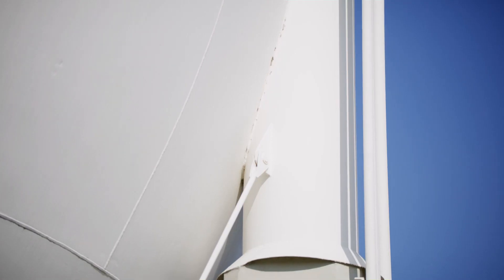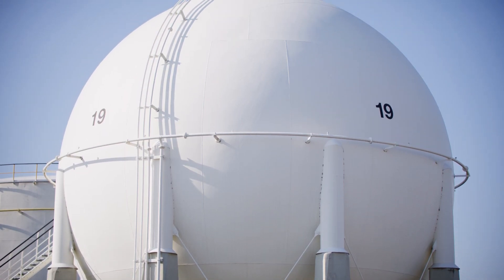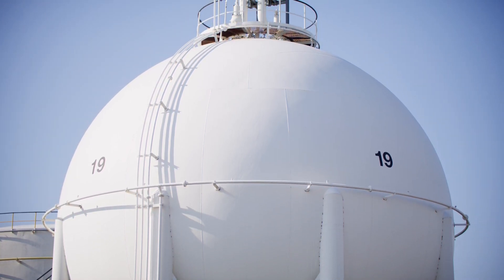What is the secret to achieving these higher durability coatings? Several layers implies a higher thickness of the coating, more durability - a longer diffusion path, making it more difficult for ions to penetrate through the paint. Such a paint consists of a primer, an intermediate coat, and a top coat - you could also say two layers of primer plus a top coat. Especially in the primer, anti-corrosion pigments are used in order to achieve this level of protection.